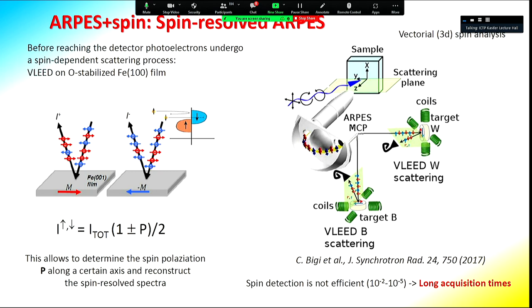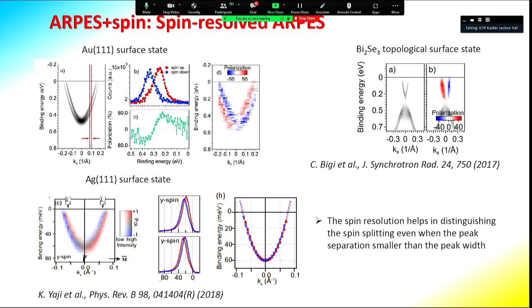One of the most advanced capabilities of ARPES is measuring the spin-resolved band structure — not only for one spin direction but for all three dimensions using vectorial spin analysis. Spin-resolved ARPES can also resolve individual bands that are so closely aligned that the bandwidth is larger than the peak separation. The time required for spin-resolved measurements is much higher — on the order of hours compared to minutes for conventional ARPES, roughly 100 times longer.